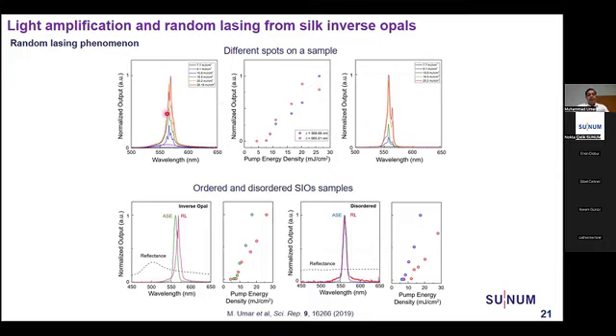inside the sample because of the fabrication. So those cavities act as a random lasing platform, and we can see very sharp spikes in the form of a random laser. These we measured at different points. As well, we checked using uniformly ordered inverse opal. So this means the photonic band gaps can also create random lasing in this structure as well.